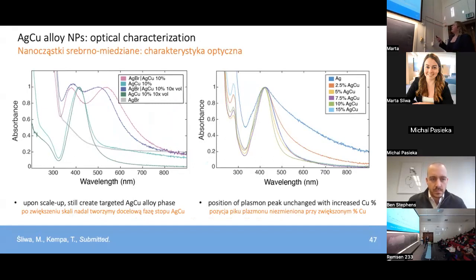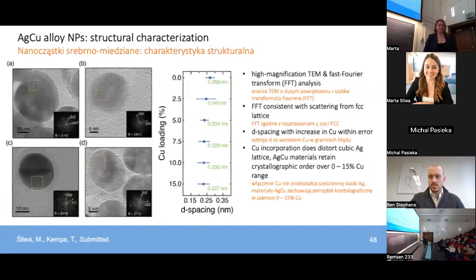As we look at the plasmon peak position over that 0 to 15% copper range, we see that there's very small shift, only about 3 to 5 nanometers as we go to higher percentages of copper. This lack of very noticeable or appreciable shift indicates to us that we're most likely forming very dilute copper and silver nanoparticles, which again, I'll also revisit in the next stage. So this all indicates the retention of this plasmon peak, that these materials are stable to oxidation, they don't undergo any morphological change when we introduce more copper, or they don't undergo any aggregation, and there is also no phase segregation into copper-rich or silver-rich areas.